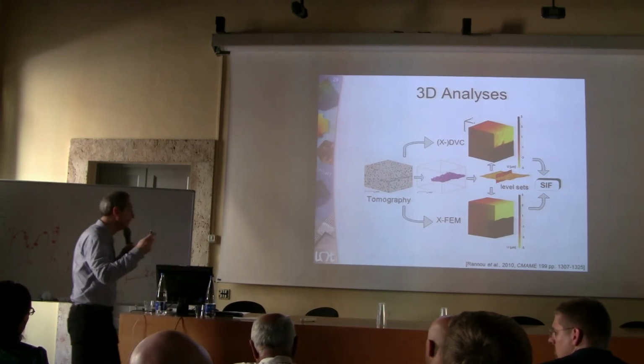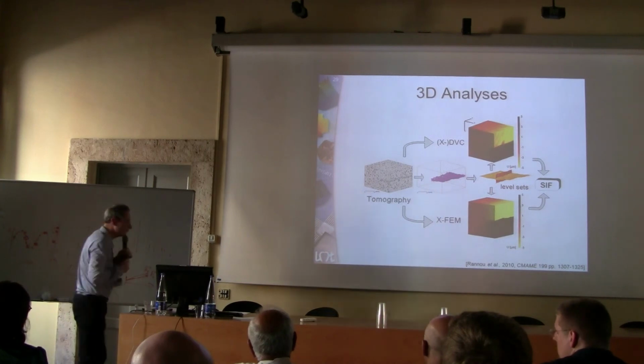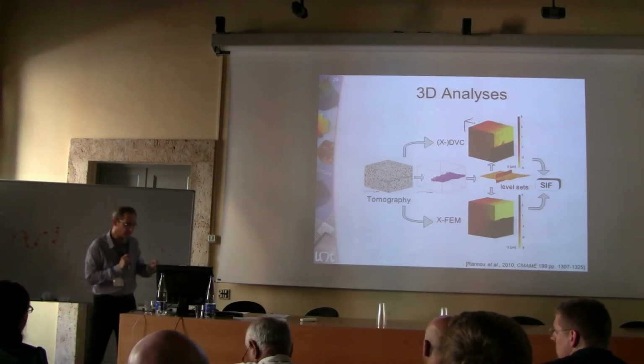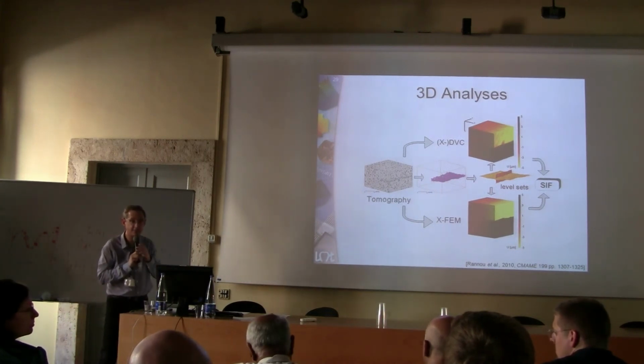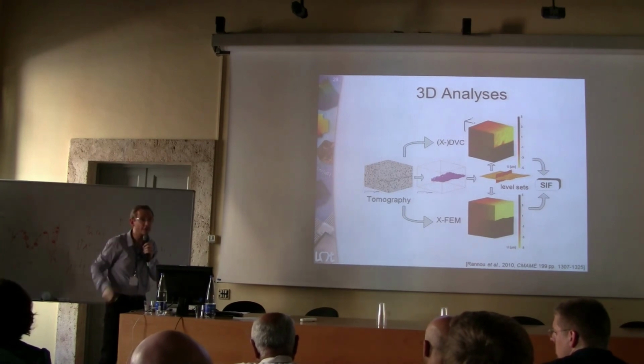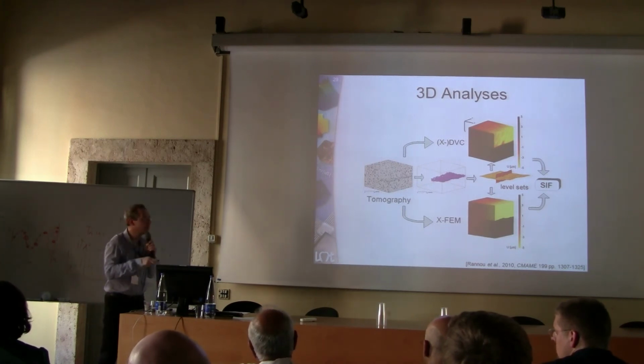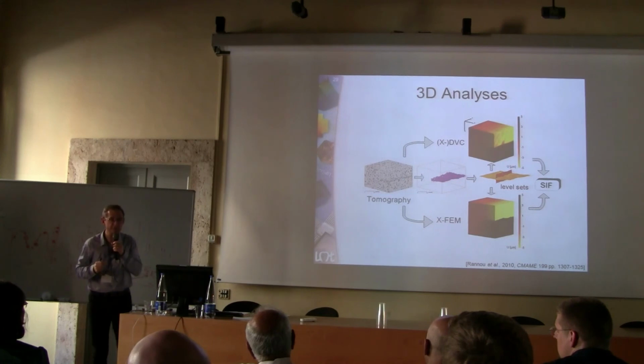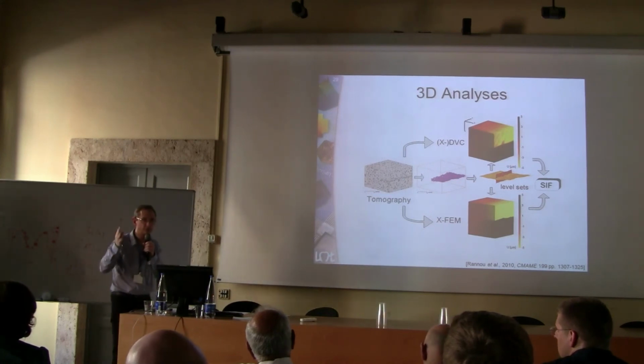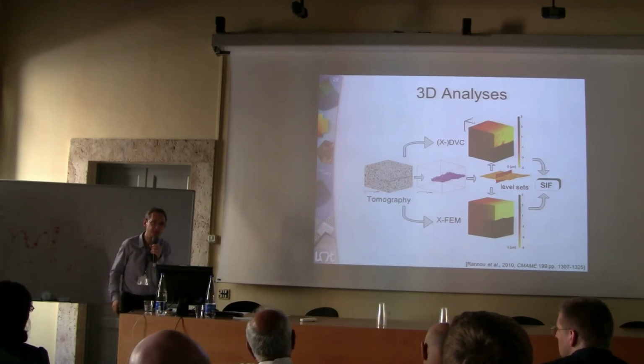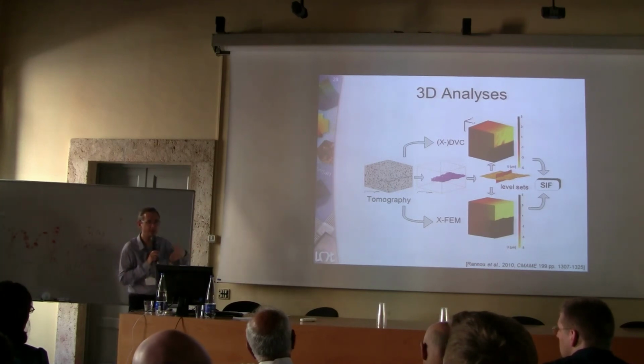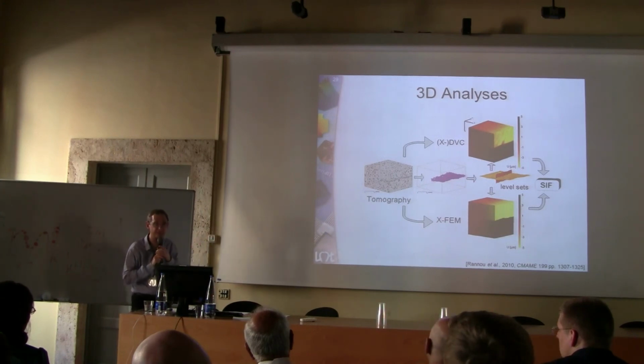The only thing that was not done, as you know, you have the Heaviside type of enrichment, and then you have also the crack tip type of enrichment. DVC is not resolved enough to add these additional degrees of freedom, which means that even in XFEM you have additional extraction techniques to evaluate stress intensity factors and things like that.